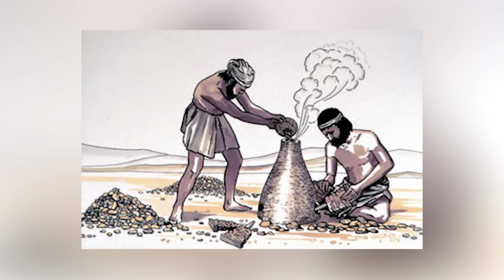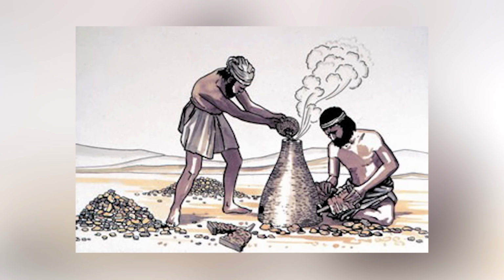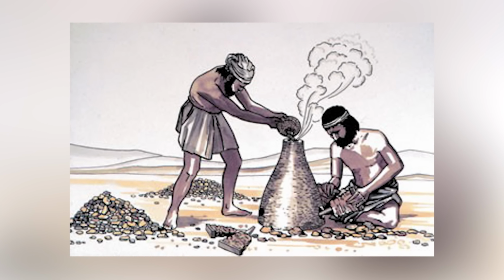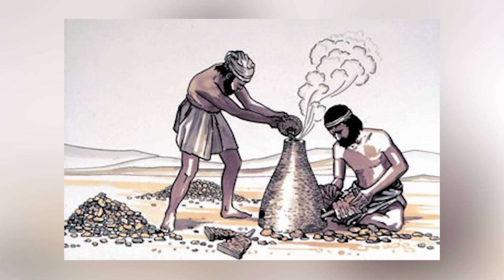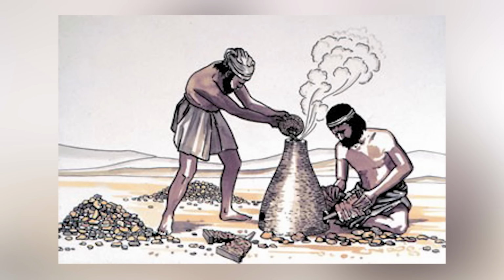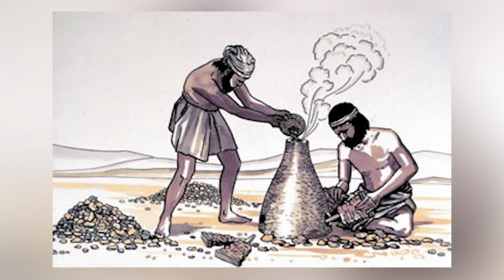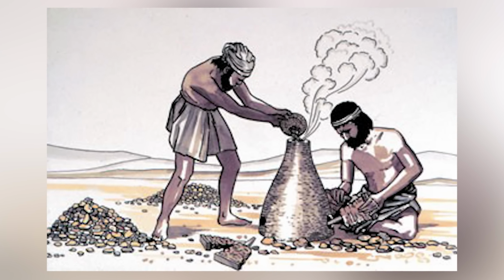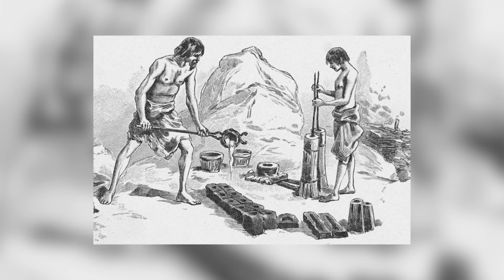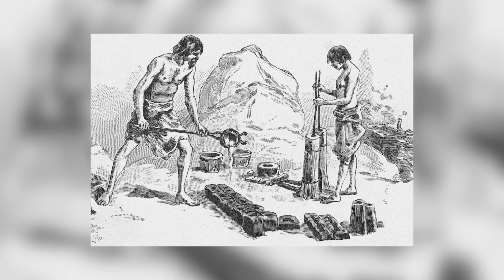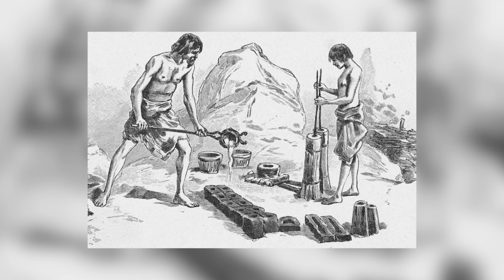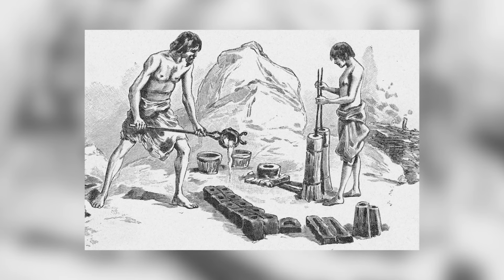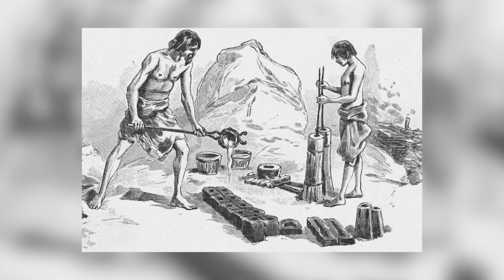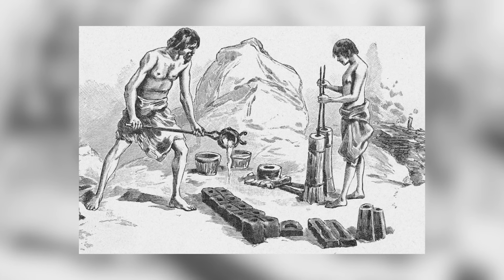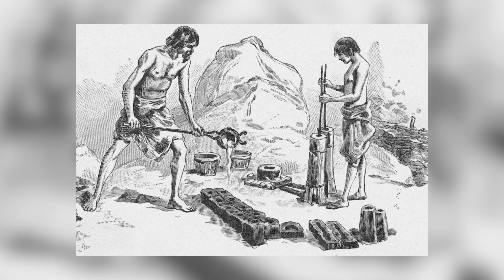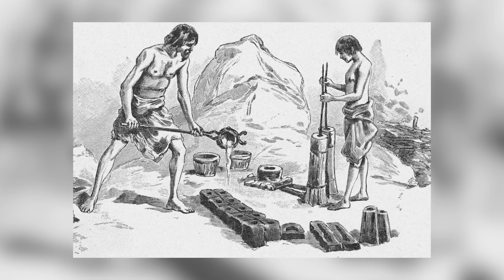These results align with historical evidence. Medieval tools that received proper hammering treatment regularly survived centuries of use. Modern press tools typically fail within years, sometimes months, under equivalent working conditions. 200 hammer strikes are not romantic tradition. They are not theatrical ceremony. They are functional engineering that transforms metal from adequate to exceptional. The difference between 3 seconds and 3 hours, the difference between using something once and using it for a lifetime.